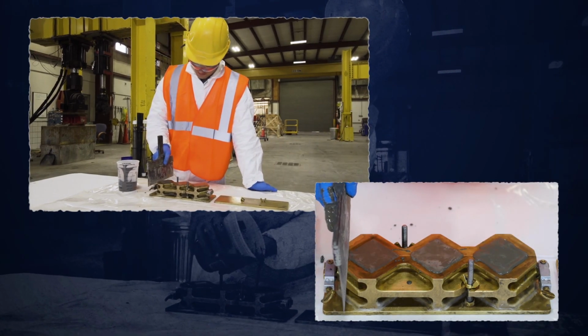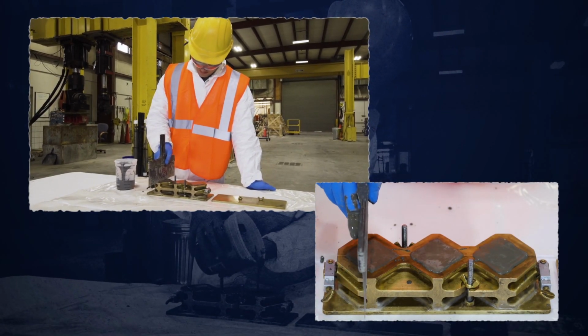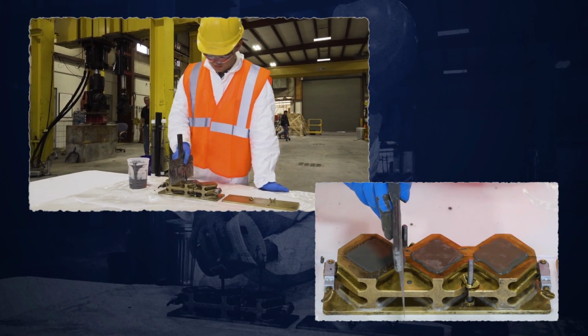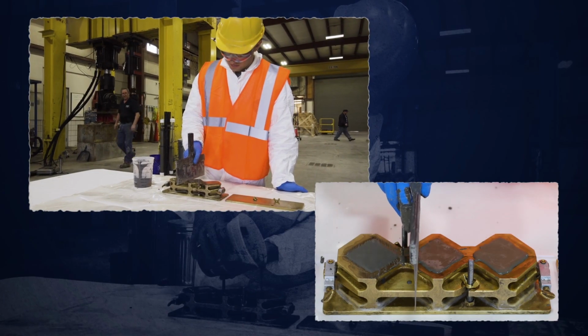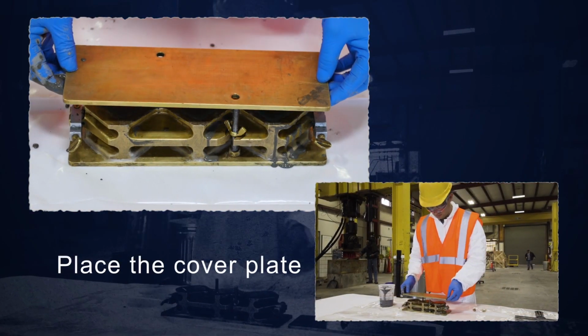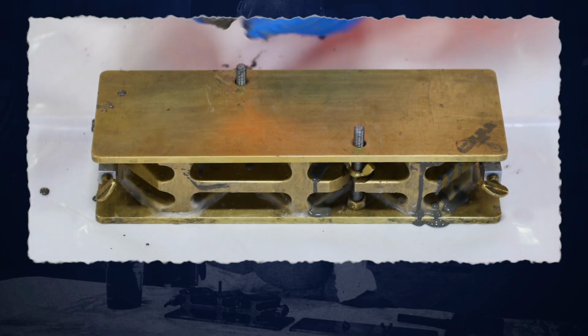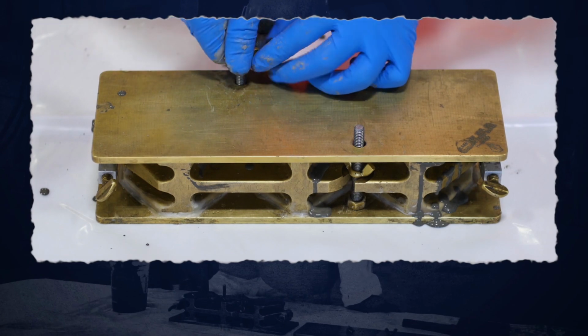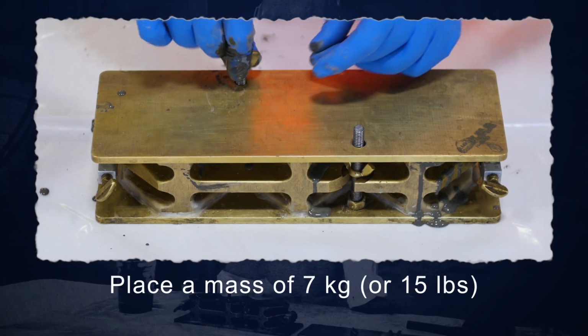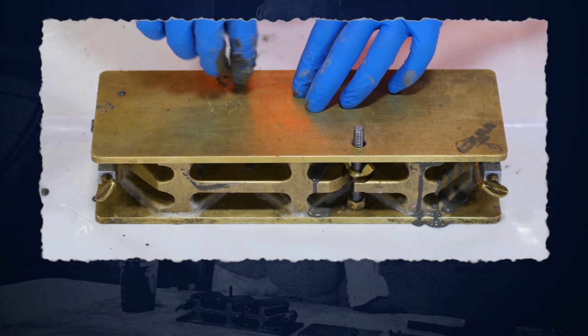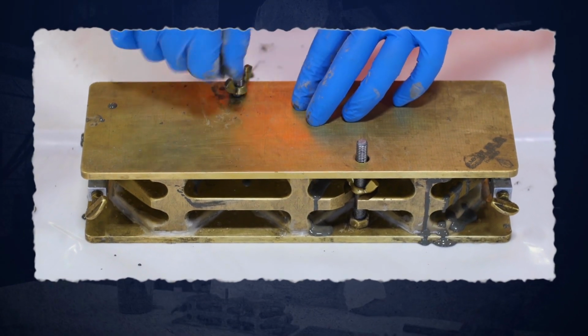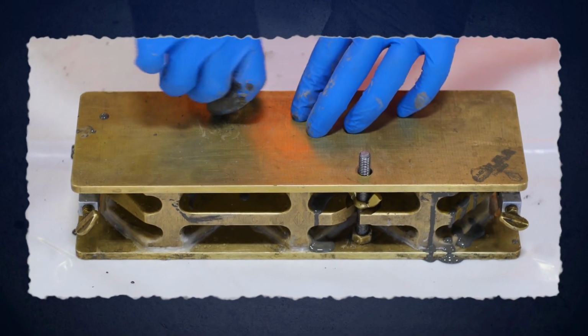Bring the excess grout to the center and finish the surface by cutting off the excess with the straight edge of the trowel held vertically and drawn across the top of the mold with a sawing motion. Place the cover plate of the 3-gang mold, taking care that the grout or loose grains of sand do not prevent seating of the plate. Place a mass of 7 kilograms or 15 pounds on each cover plate, or fix the cover plates with the molds with attached clamps.